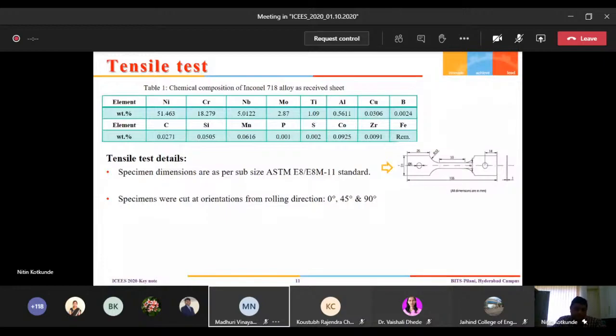As I mentioned, sheet is highly anisotropic, so it is very essential to test the material properties at different rolling directions. Usually 0 degree is considered the rolling direction of a sheet. Then at minimum we have to test at 3 different conditions: 0 degree, 45 degree and 90 degree orientation.